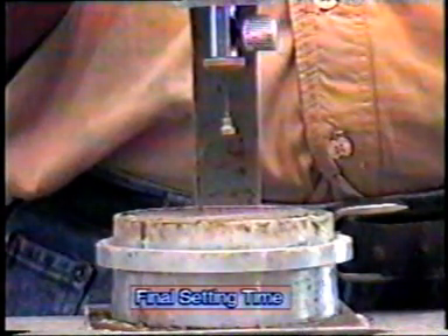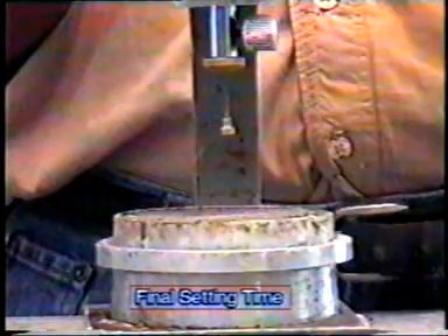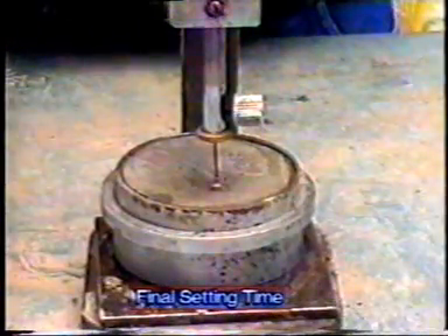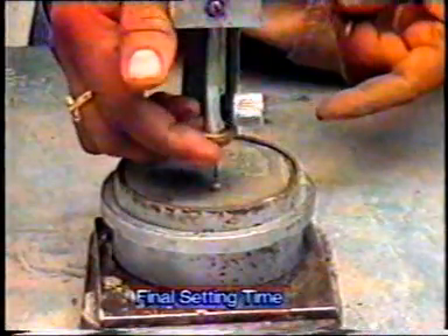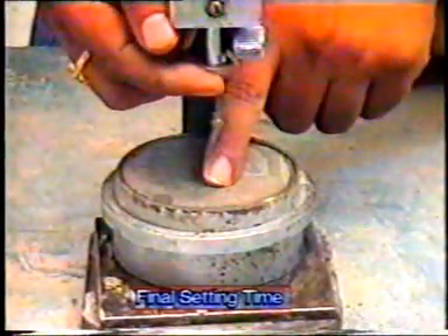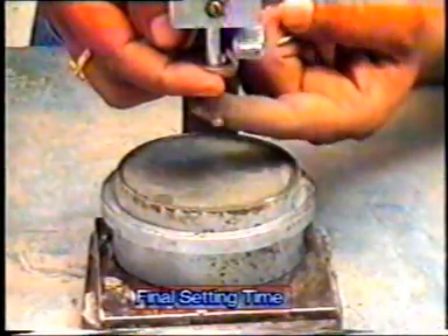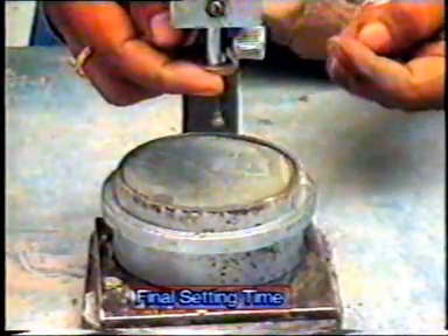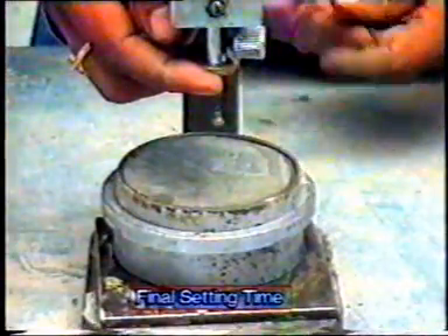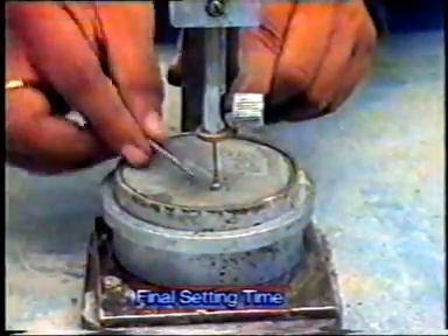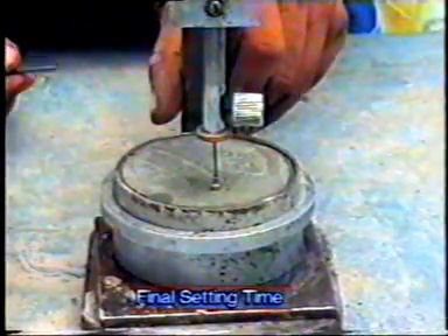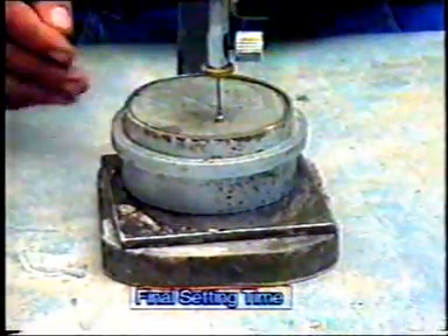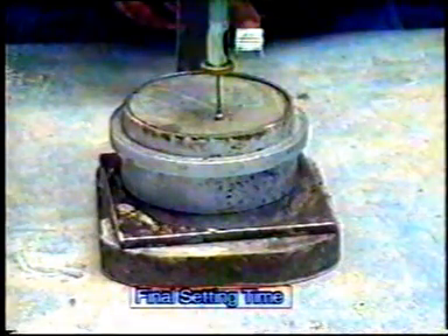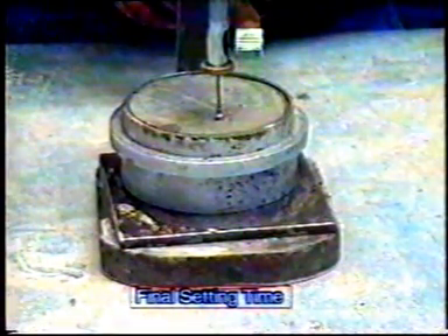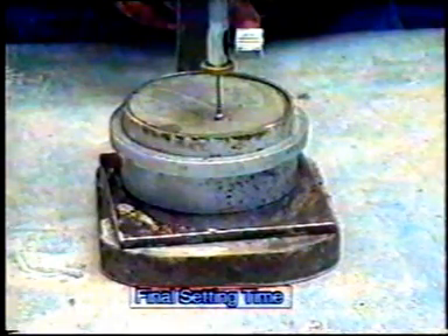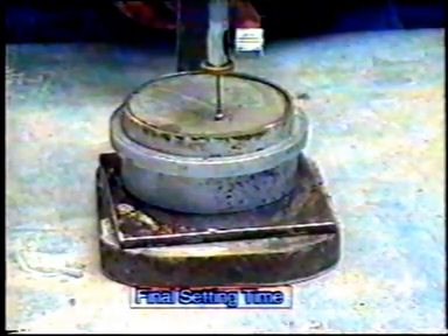This process of application of the needle is repeated until the needle makes an impression on the test block but the outer ring fails to do so. Now as you can see, the inner needle of the Vicat's apparatus made an impression but the outer ring has failed. This indicates the final setting time of the cement.